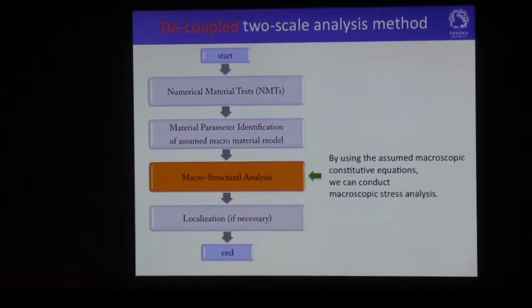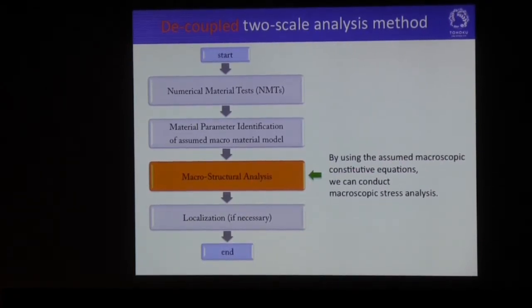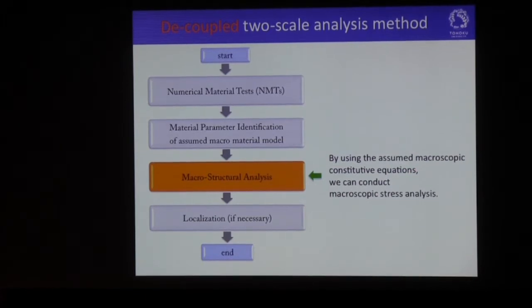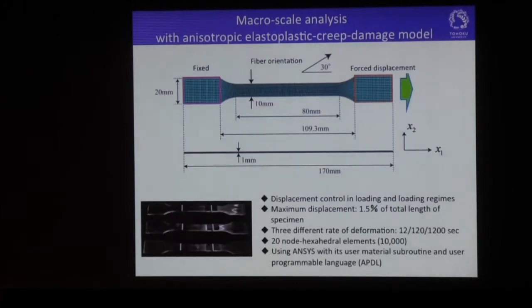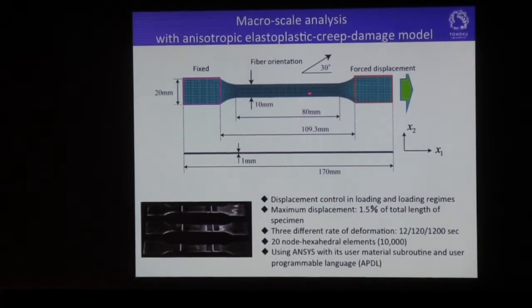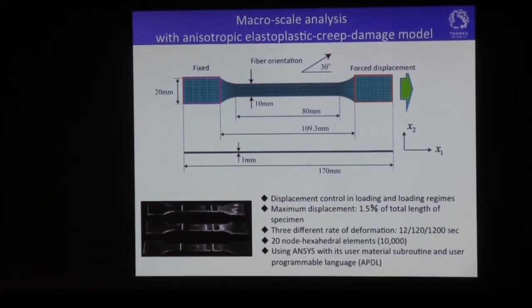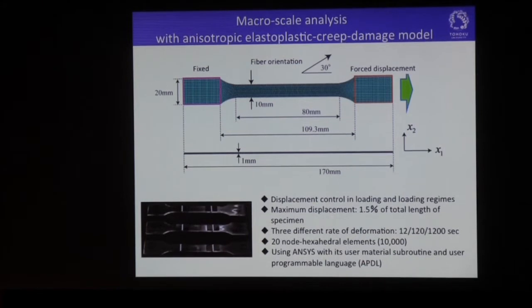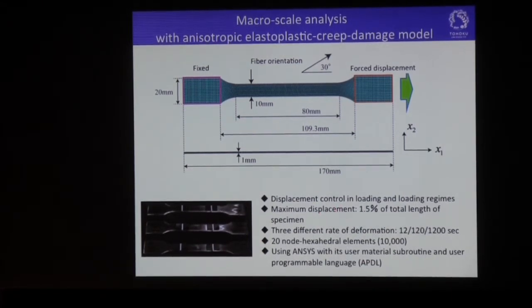By using the assumed macroscopic constitutive equation and also the material parameters identified, we can conduct the macroscopic stress analysis. Here, this is my macroscopic structure, which is the typical specimen of the fiber reinforced composite. To demonstrate anisotropy, the fibers are oriented in this direction. These are the analysis conditions, but the details of the conditions are not important in the context of this demonstration.